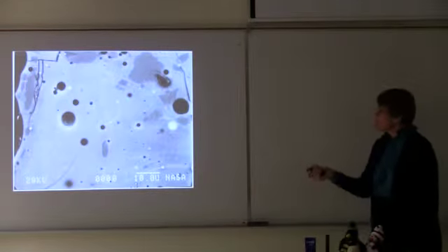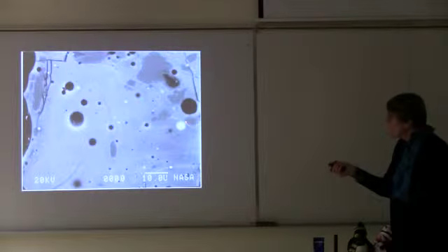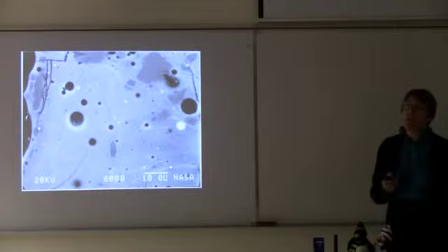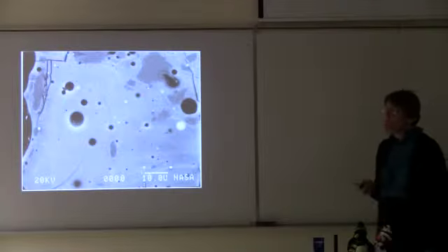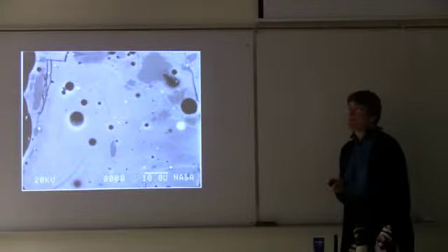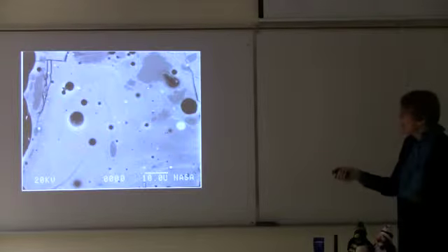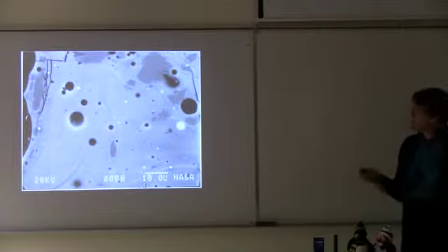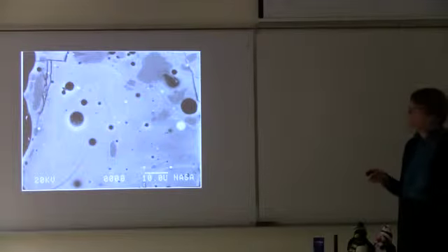So my original work started with the lunar agglutinates with Dave McKay, who was a big moon guy. We were interested in measuring the abundance of these very fine nanoparticle-sized iron blebs. And so we had been working with the scanning electron microscope with backscatter imagery and using NIH Image then to evaluate to see if we could measure the abundance of these little teeny blebs, because they are very bright, so in grayscale, they differentiated from the rest of the meteorite, so we had ways to get at doing this.